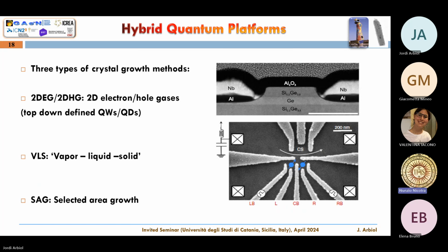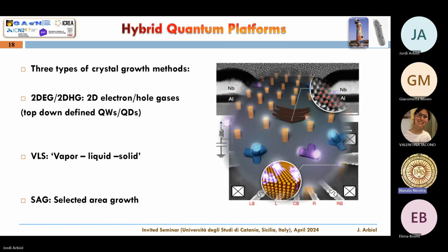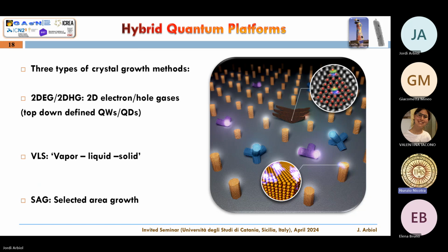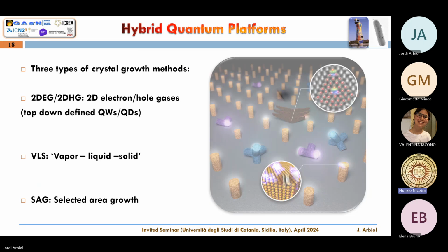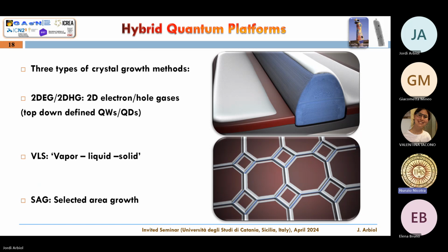So this is for the two-dimensional electron gas, hole gas. Then there is this option with VLS, vapor-liquid-solid nanowires, the ones that are standing up. So this is the first technology I was telling you about. And then the last one, which seems to be the one that is preferred for technological reasons, is selected area growth, in which you can grow the nanowires directly on top of the substrate and create these interconnected networks directly. Okay, that would be the easiest solution.